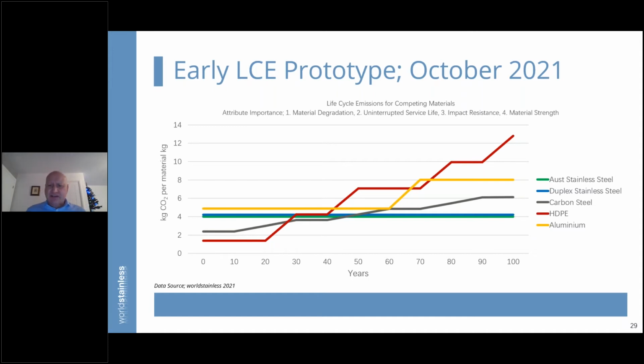So thinking about those things, we looked at two different stainless steels, an austenitic and a duplex, a carbon steel, a high density polyethylene, and aluminium. And on year zero, on the right hand side, from an emissions perspective, the plastic product, the HDPE, looks very interesting. It's much lower, much lower than the rest. And all the rest sit in differing positions.